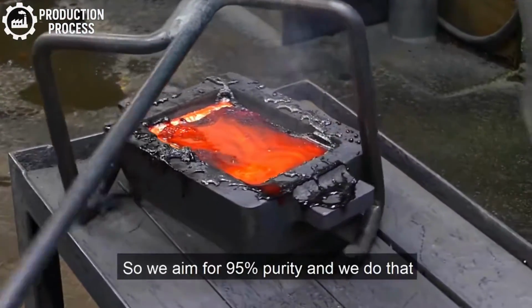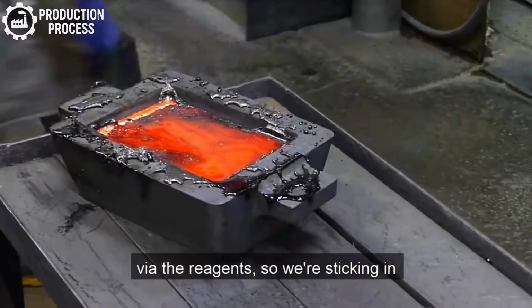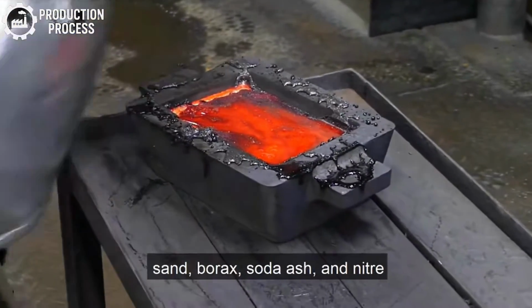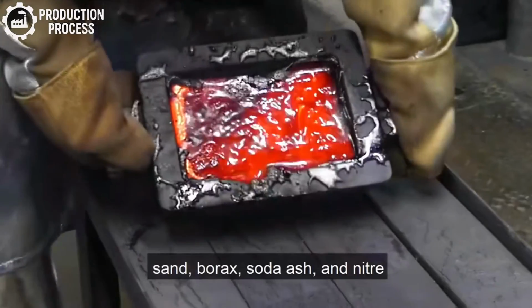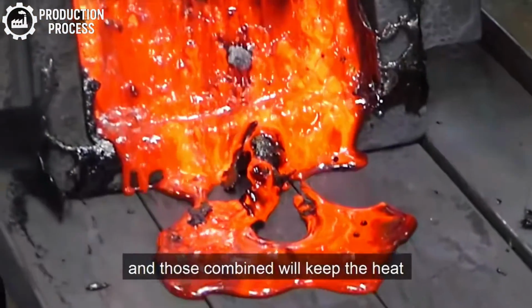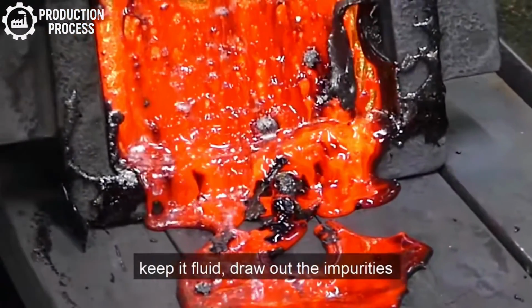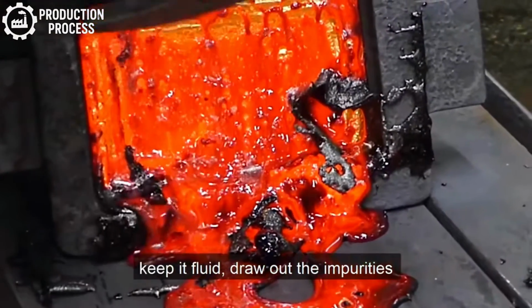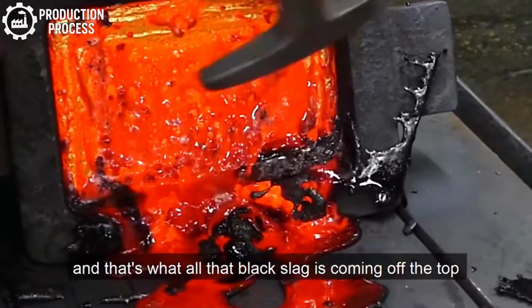So we aim for 95% purity, and we do that via the reagents. So we are sticking in sand, borax, soda ash, and niter, and those combined will keep the heat, keep it fluid, draw out the impurities, and that is what all the black slag is coming off the top. So it is not gold, it is black like obsidian.